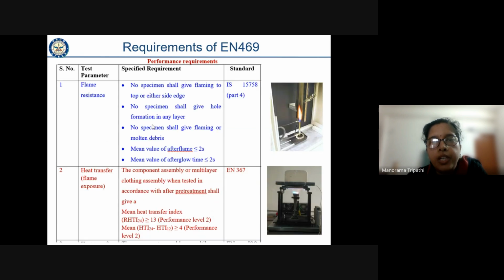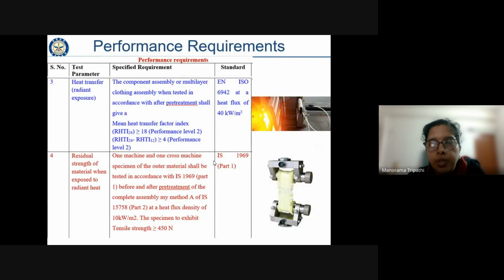These are the requirements of EN 469, which a fabric should meet to be used in fire protective gears. Flame resistant: no specimen shall give flaming either at the top or on either side edges. No specimen shall give hole formation in any layer, and no specimen shall give flaming or molten debris. Mean value of afterflame should be less than 2 seconds, and mean value of afterglow time should be less than 2 seconds. So these are the performance criteria. I would not go into much detail.